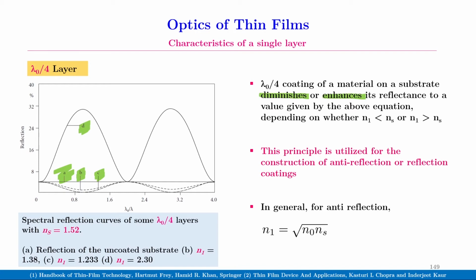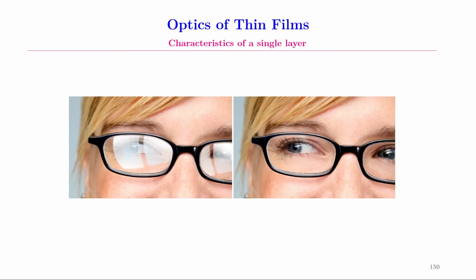In general, for anti-reflection coating, the refractive index of the film has to be the geometric mean of the refractive index of air and that of the substrate. That is n1 equal to the square root of n0 times ns. This figure shows the use of anti-reflection film on a pair of spectacles.